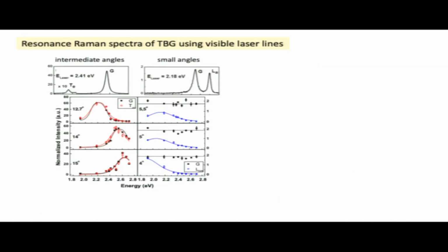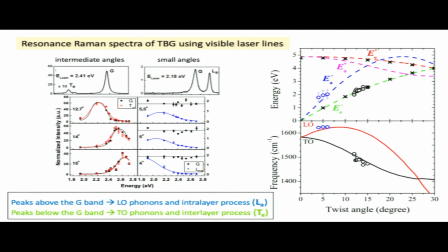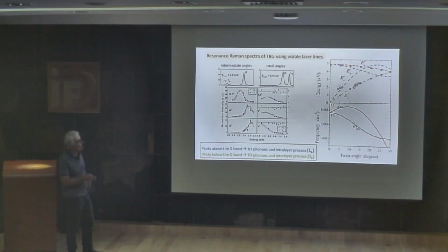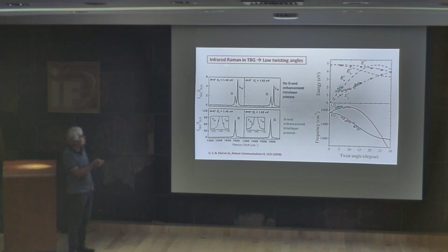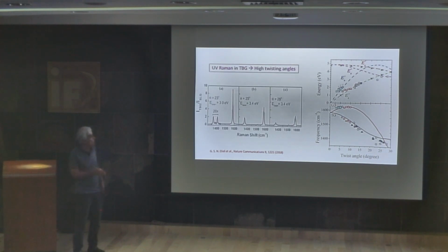Then what we could show in this paper is that we could see, for example, here, using a visible laser, that the peaks that are below the G band are enhanced by the interlayer process, and the peaks that are above are activated by the intralayer process. Okay, then we did some measurements using also an infrared laser, because if you need to study low angles, you need to use infrared lasers, and we could put some points here showing that we can have both processes. And for a higher angle, then we need to use UV Raman, because with UV Raman you can see angles of more than 20 degrees.